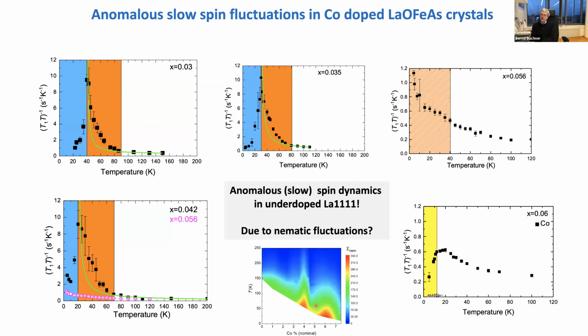So we have these very soft nematic fluctuations, a very soft lattice, a very soft orbital degree of freedom, and an extremely soft spin degree of freedom. And all of that is strongly coupled to electron transport. Therefore it's apparent that you have this extremely strong scattering of the electrons, and this explains, at least qualitatively, that you are very close to localization. And only if you go to very high doping do these things disappear and things more and more become like usual metals.